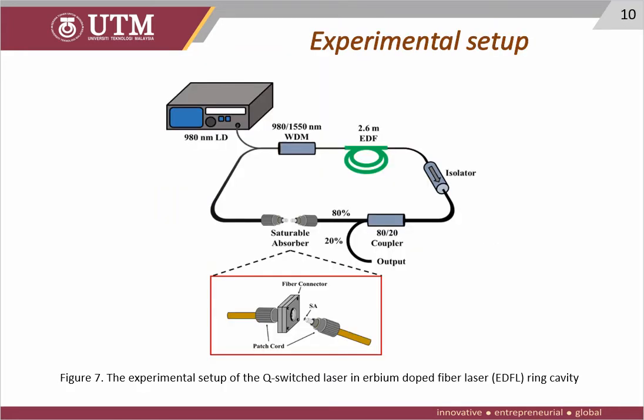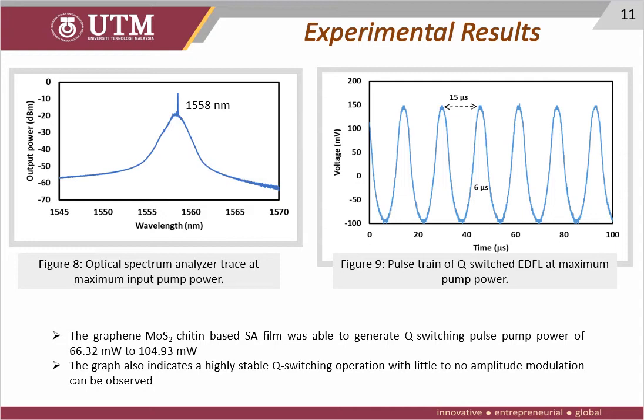Okay, this is the experimental setup of the Q-switched laser in an erbium-doped fiber laser ring cavity. So we sandwich the SA in the fiber ferrule here. For the result from the Graphene-MoS2 chitin SA based material, we got a 1558 nanometer wavelength from the optical spectrum analyzer at the maximum input pump power, and the Graphene-MoS2 chitin based SA film is able to generate Q-switching pulses from 66.32 milliwatt to 104.93 milliwatt input pump power. Figure 9 shows the graph of the pulse train. The graph indicates a highly stable Q-switching operation with little to no amplitude modulation observed.